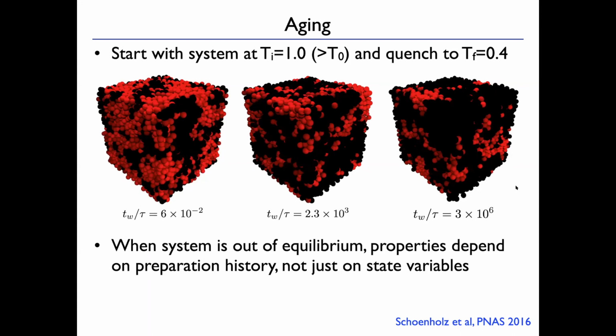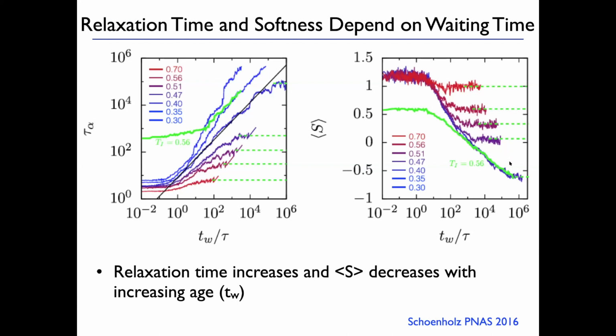And because the system's out of equilibrium, the properties depend on the preparation history. When did I quench it? Where did I quench it to? And not just on the state variables, you know, what is the temperature and pressure I'm at now? Okay. And what happens is that as you follow these things in time for different starting temperatures, different ending temperatures of my quench, I can plot the relaxation time and it changes with time, okay? And similarly, the average softness, as I showed you, decreases with time.